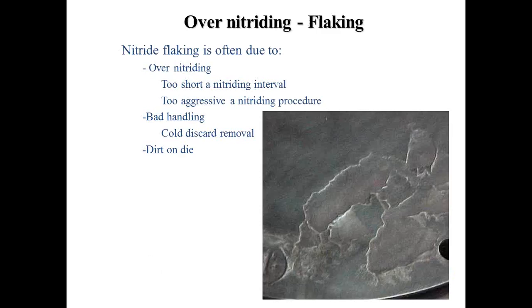If we take over-nitriding to its limits, we start to see this. This is the face of a flat face die, where people have tried to shorten the nitriding interval by making the nitriding parameters much more aggressive. And I will come back to the role of the different parameters and how they interact in getting a good nitriding layer.